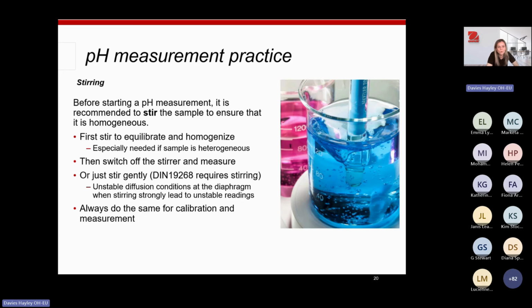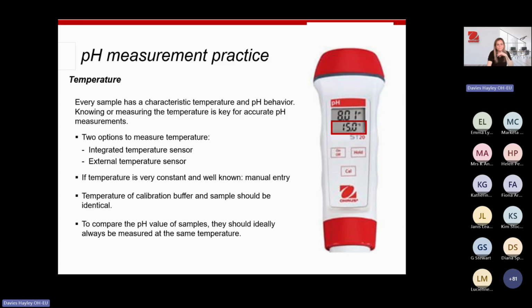If your method requires DIN 19268, which does state that it needs stirring, then it's recommended you just stir it gently. By that we mean just pop your probe into the solution and give it a little stir, just like that. Not like you're cooking, stirring the chili on a Saturday night, just a little gentle stir and that should be fine. And always make sure that whatever you do for the calibration, you do for the measurement and vice versa, because it needs to be consistent in the way that you're measuring your samples.